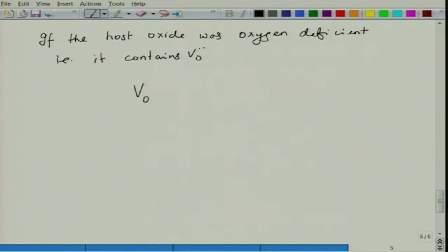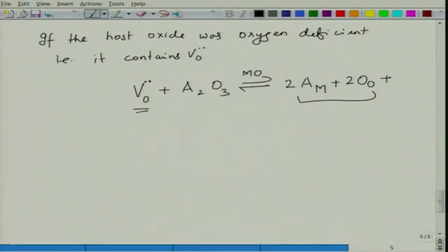You have oxygen vacancies present in the system, which means if I am doping the oxide with higher valence, I am bringing in extra oxygen to the system. So, if I am bringing in A2O3 and this goes to MO, then basically 2 A's go to M site, 2 O's go to oxygen site to maintain the site stoichiometry, but you have one oxygen vacant site. This oxygen vacant site can be filled by this again oxygen site. So, now you do not disturb the site balance. You had one site here, you have filled that site with extra oxygen, and two other sites which were created, they are balancing each other. So, this is basically another way.